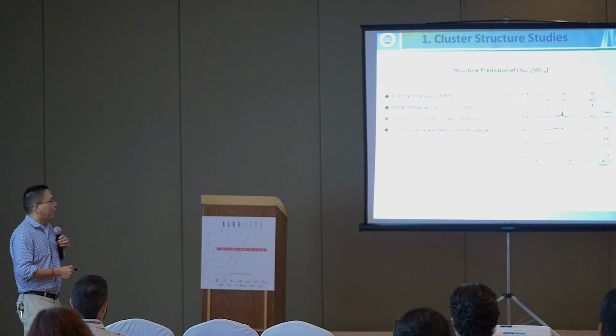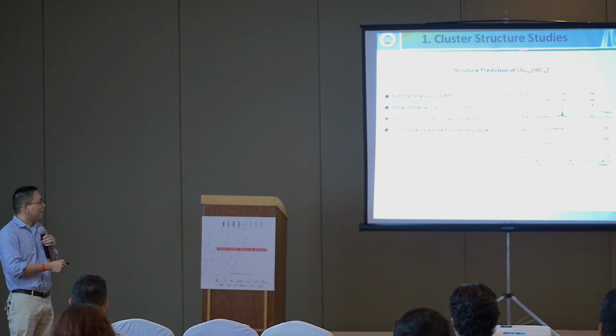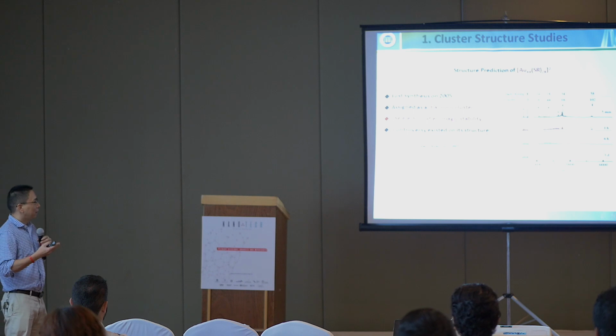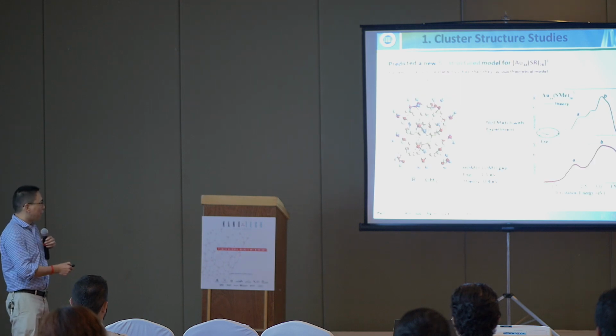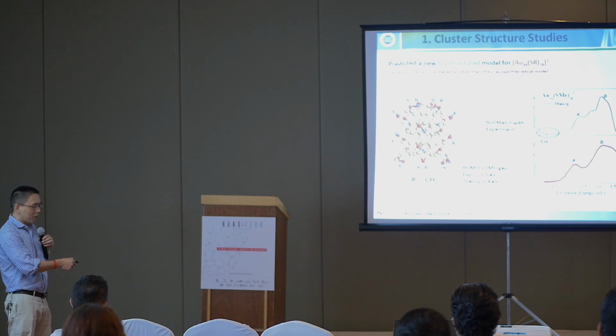So with this knowledge, we carry out structure prediction for Au144. This cluster was first reported by Professor Whetten in 2005, and lately it was also detected in later synthesis. But for a long time, its structure was unknown. And using our method, finally, we obtained a low-energy, stable structure here. Surprisingly, it's also an FCC structure.